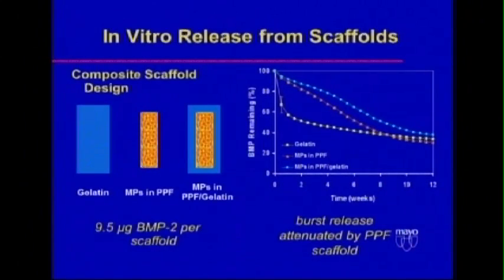So here's just to try that. I asked Dieter and Li Chun to make a couple different diffusion paths because, again, from a clinical need, one of what we perceive as a problem with the BMP specifically is it's so expensive, and there's a burst release, and we take this incredibly expensive molecule and throw half of it away in the first day or two as it leaches out. And I would also submit that when I close a wound, the first thing in the space where I want bone to form is a hematoma. And there's no cells there for that BMP to act on.